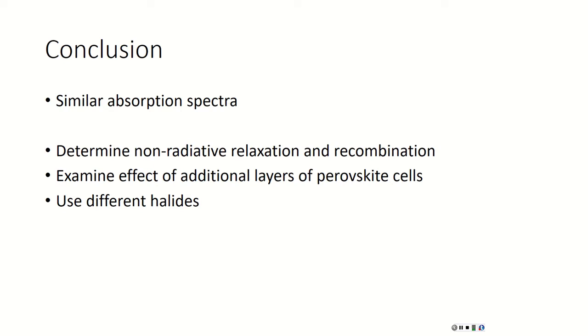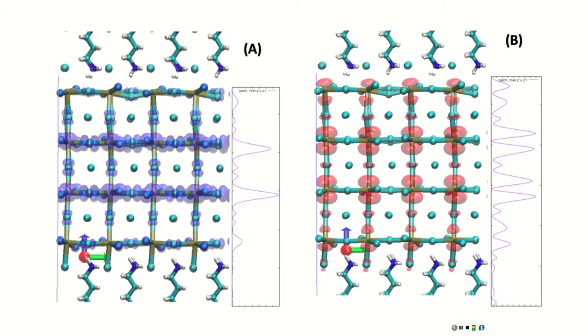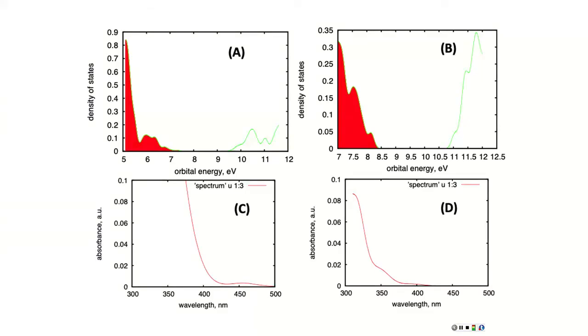Yeah. Can we go back to your density of states? I noticed it looks like B is a larger gap. B does have a larger gap. It was approximately a 2.8 eV gap for the Ruddlesden-Popper phase, where the hybrid had approximately a 2.3 eV gap. What do you think accounted for that change?